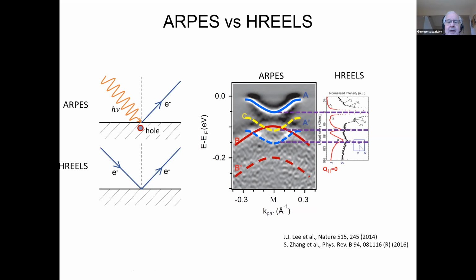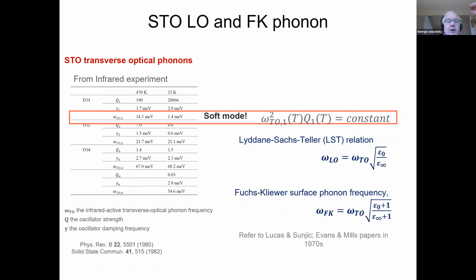actually in the electron energy loss. So the electron energy loss stuff is very well understood. It's from way back when in the 1970s, Fuchs and Kliewer and so on, they did this work on surface phonons, which basically in this case are the longitudinal optical phonons of the bulk, which are shifted a bit at the surface. Okay, and you can get everything just from the infrared data. We have no adjustable parameters. Everything comes from the infrared data, where we have all of the phonon frequencies.